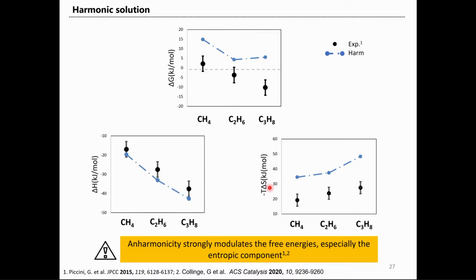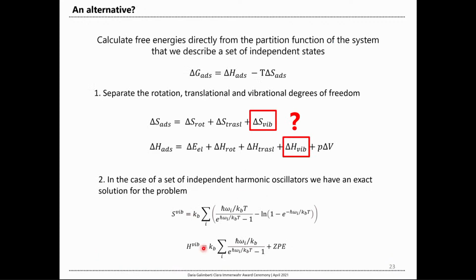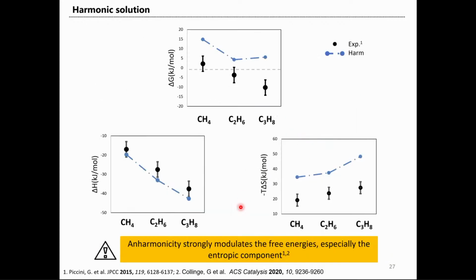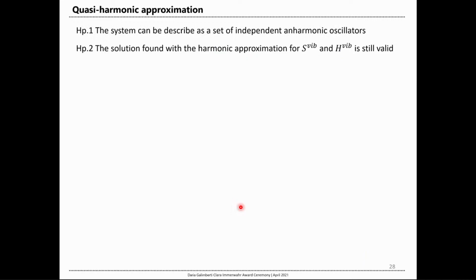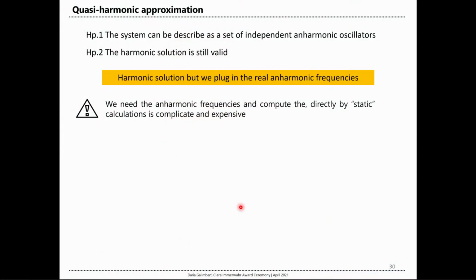So how to do this? What has been proposed in the past is that maybe this equation that I showed you here can still be used, but instead of plugging in the harmonic values for my modes, I use the anharmonic frequency. And I can tell you this worked quite well, but we have solved a problem and opened a bigger one. Because if you ever tried in your life to compute an anharmonic frequency, you know that computing an anharmonic frequency with a static calculation, as you do for the harmonic ones, is not only expensive, but really not trivial. And so we are coming back to our initial problem.